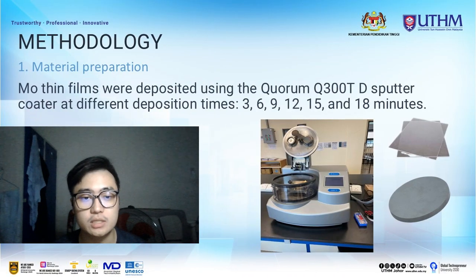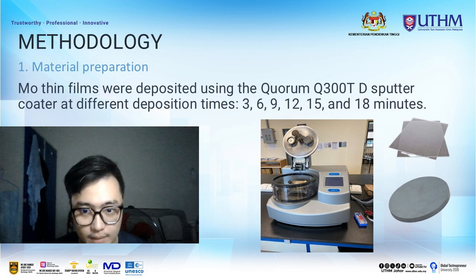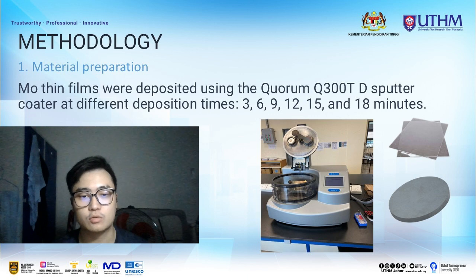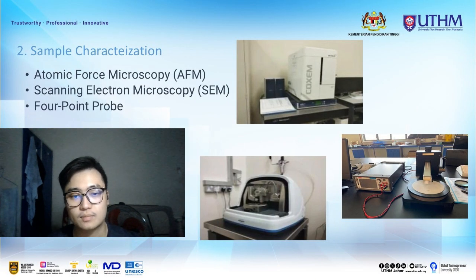As for methodology, the Mo thin films were deposited using the Quorum Q300TD sputter coater at different deposition times, which are 3, 6, 9, 12, 15 and 18 minutes. After deposition, I used three characterization tools to characterize the thin film, which are SEM, AFM and 4-point probe.